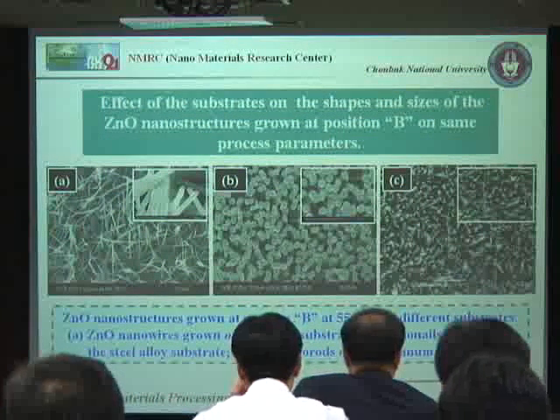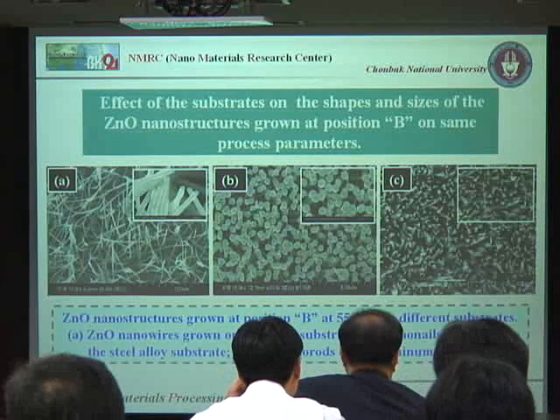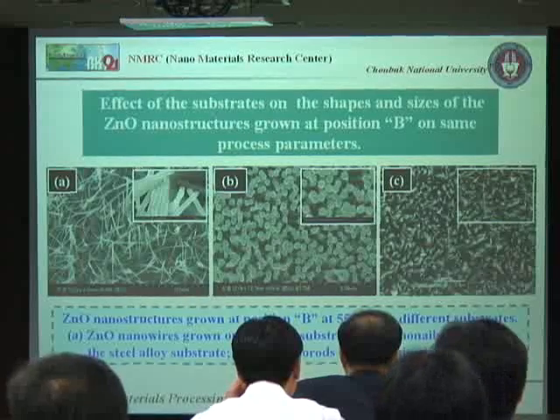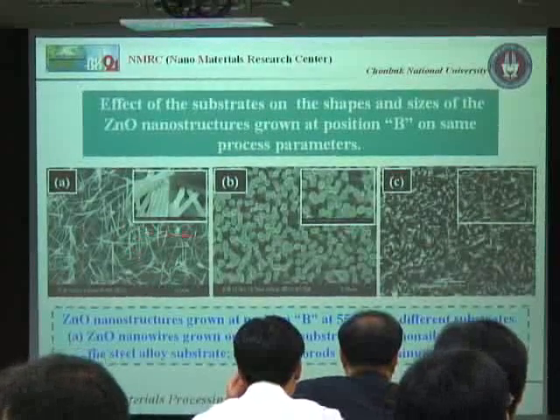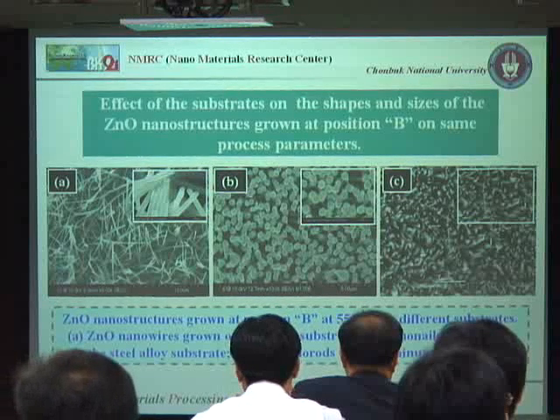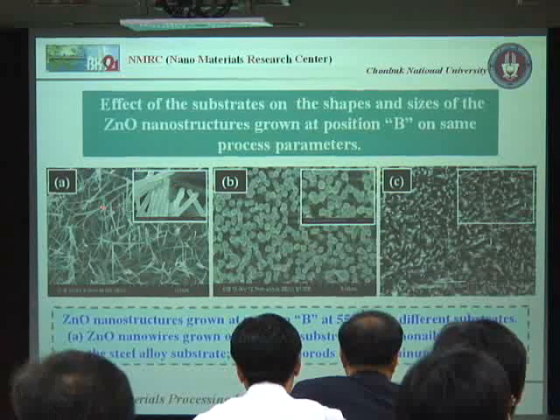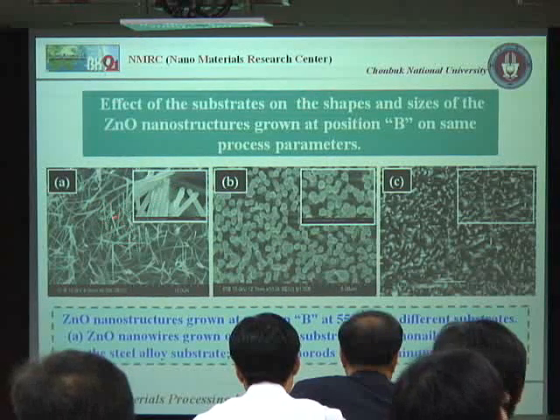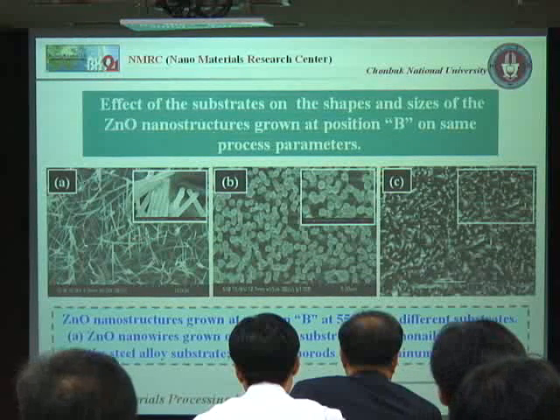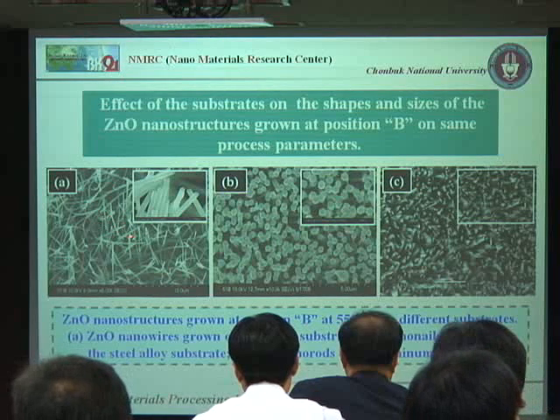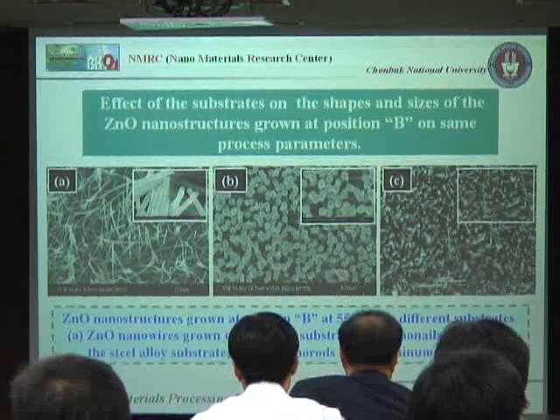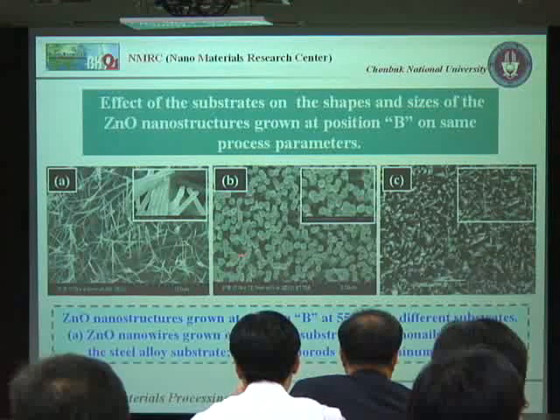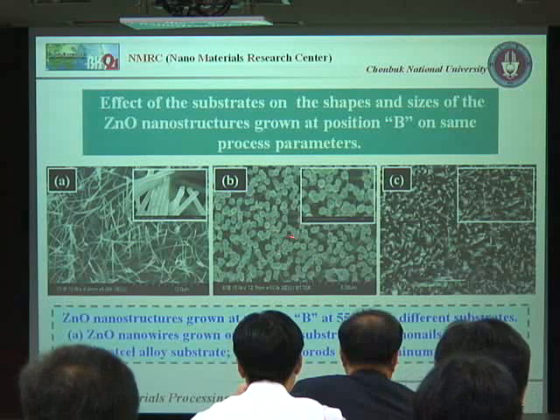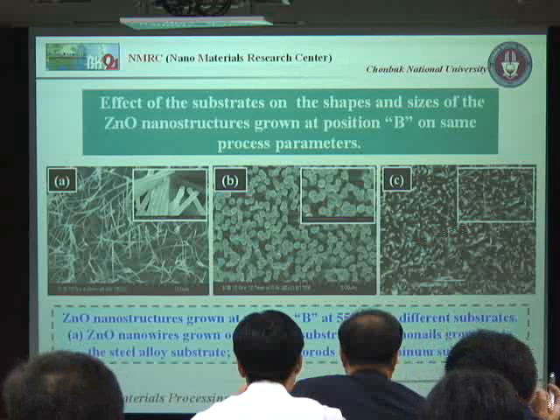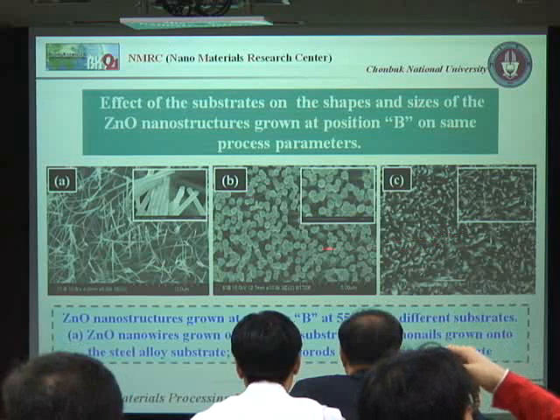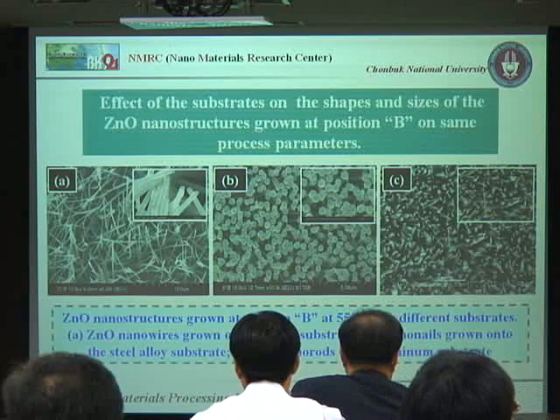Also, to check the substrate effect on this reaction, we did some experiments on different substrates at the same reaction process parameters. And we got that when we apply the same process parameters on the silicon substrate, we are getting these single crystalline, hexagonal shape zinc oxide nanowires in a high density on the whole substrate surface. We can see clearly that these nanowires are not aligned, but the shape of these nanowires is perfectly hexagonal. In case of steel substrate, we got these nanonails, and in case of aluminum substrate, we got these aligned nanorods, not nanonails or nanowires, at the same experimental process parameters.